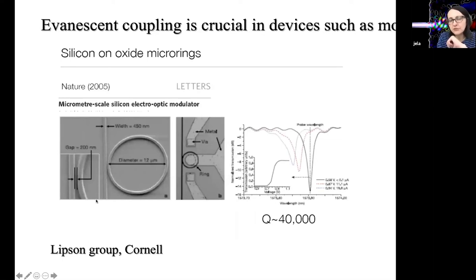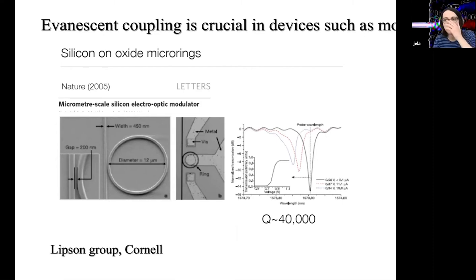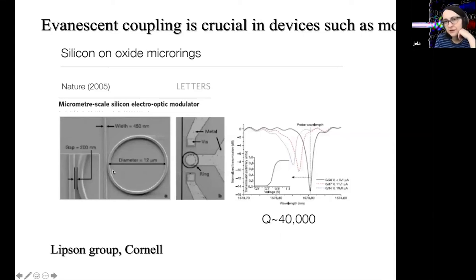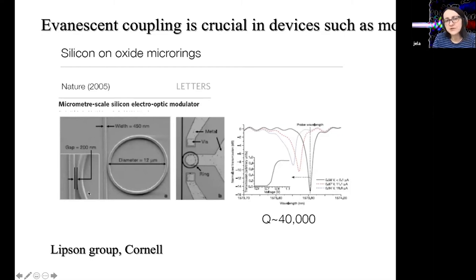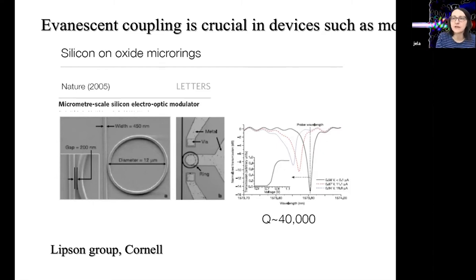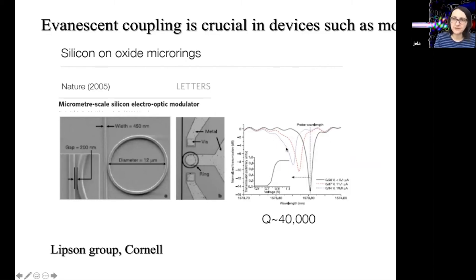Another application where ring resonators are used a lot is the ring resonator-based modulator. If you're building an integrated silicon photonic circuit, you can order ring resonator modulators. These modulators work by changing the refractive index of the resonator by some process — typically people use free carrier injection, but other processes are also possible. Free carrier injection into a silicon ring changes its refractive index; the injected carriers blue-shift the resonance because they reduce the refractive index. The resonance shifts towards shorter wavelengths, and you also see broadening because the injected free carriers introduce an imaginary part to the refractive index, introducing losses.